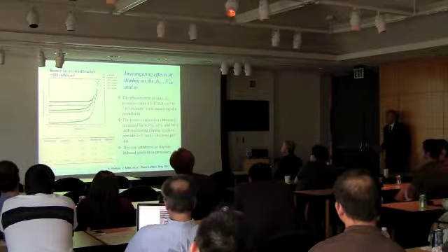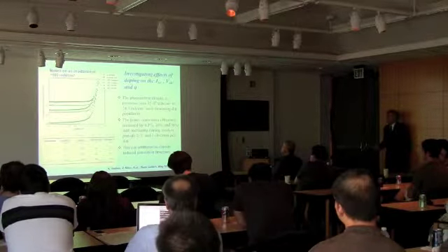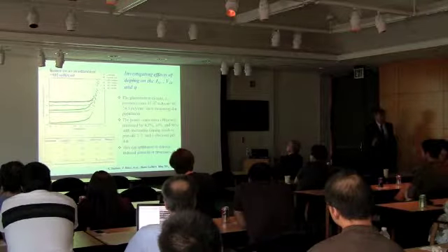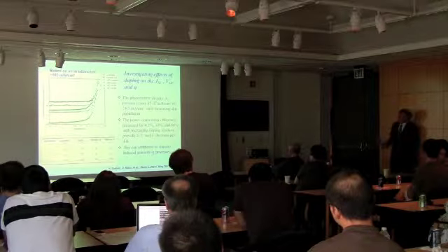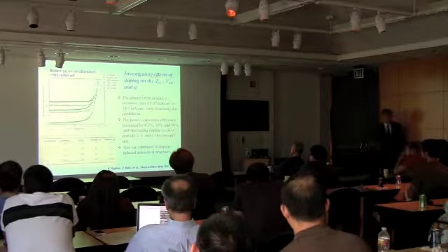If we put in quantum dots and do not dope at all, then our solar cell will give approximately the same current, a little bit smaller voltage, so practically almost no change. So it's already a good sign, because in the previous example I showed you that some people have deterioration, but there are some other publications where you have a small increase.